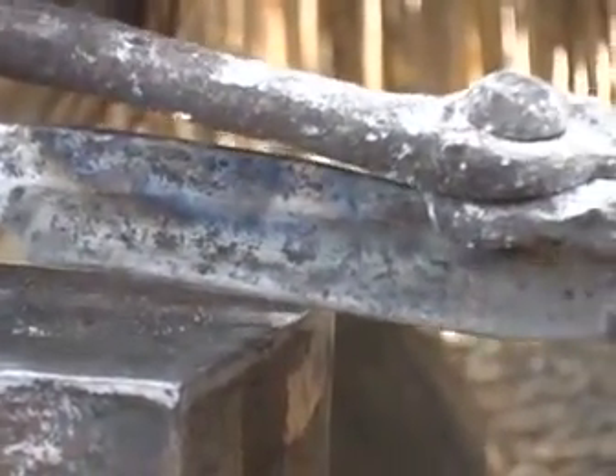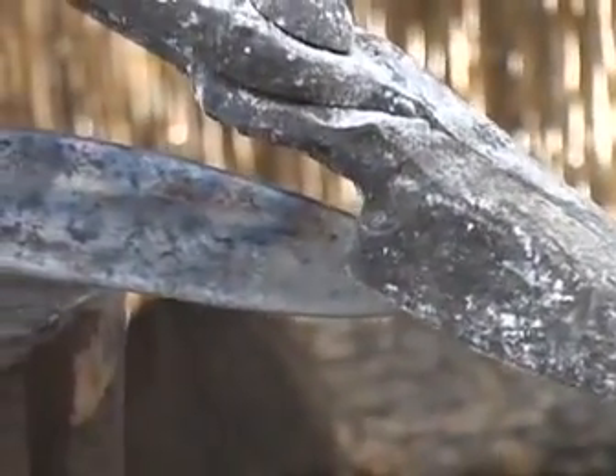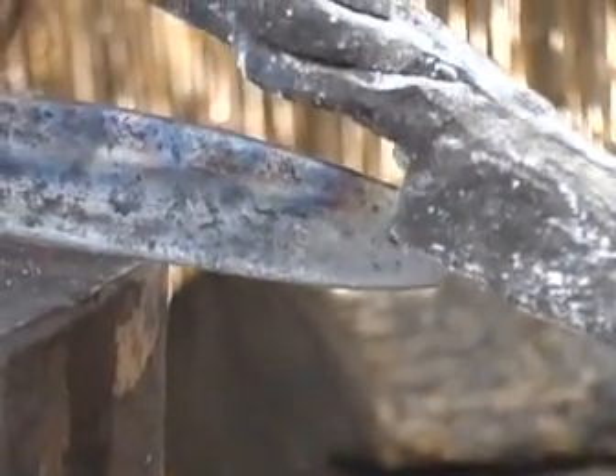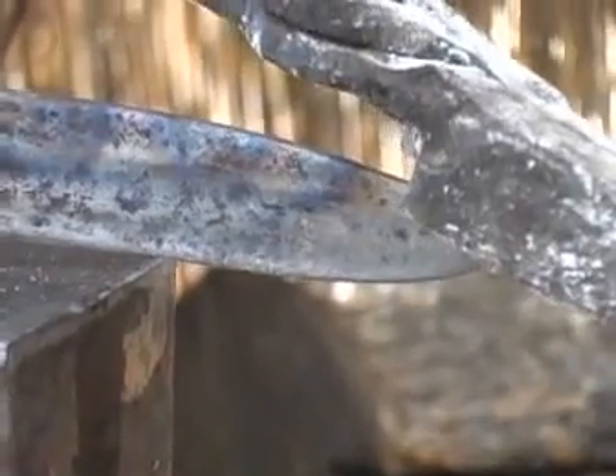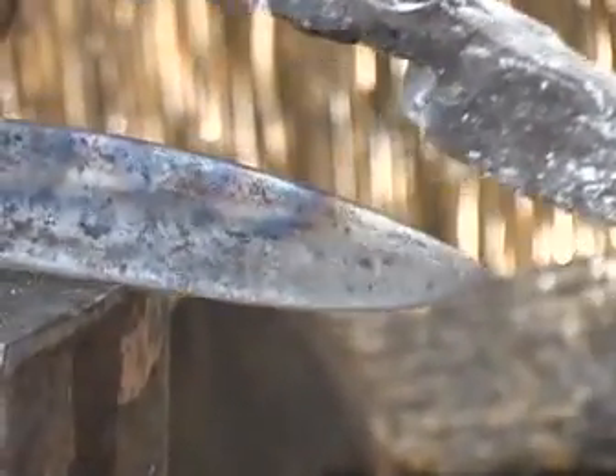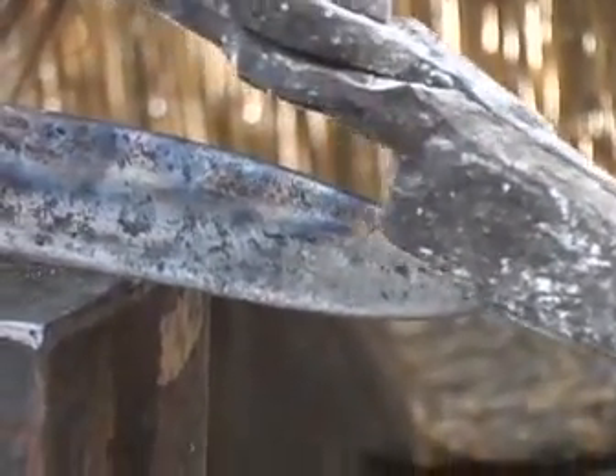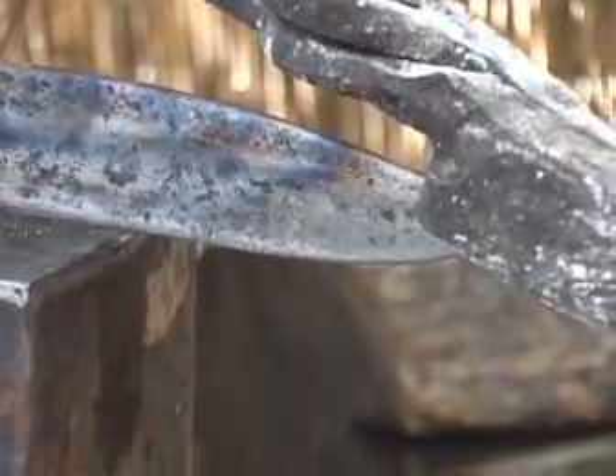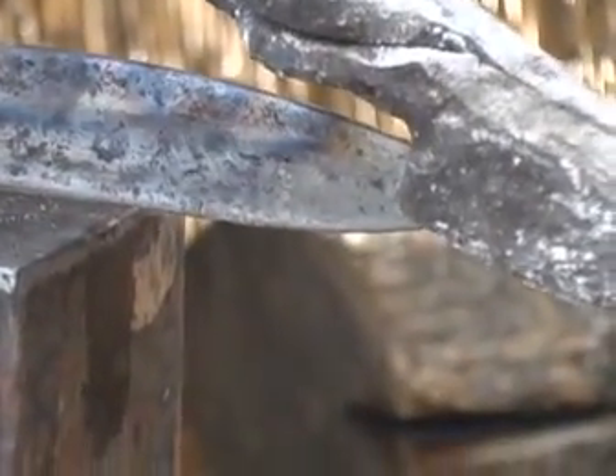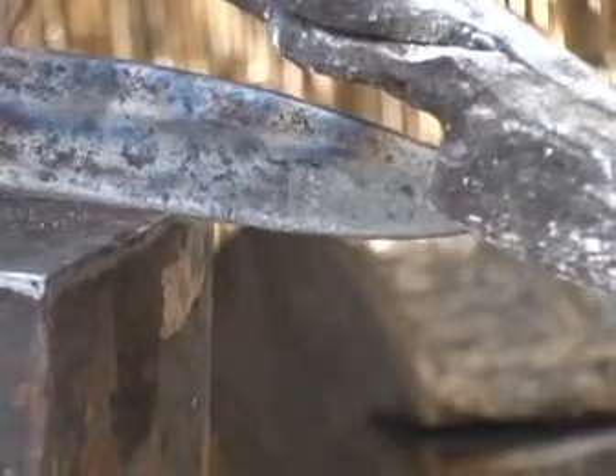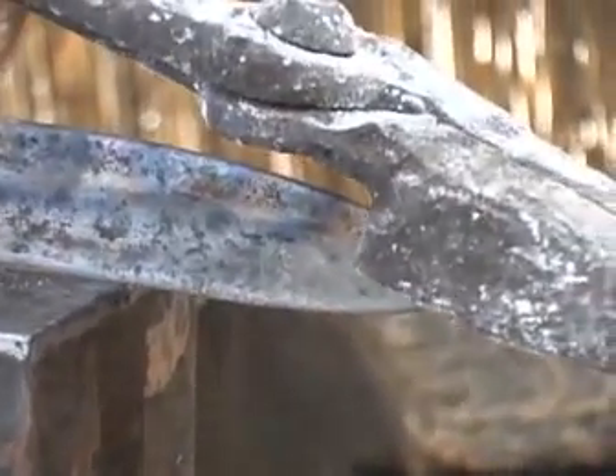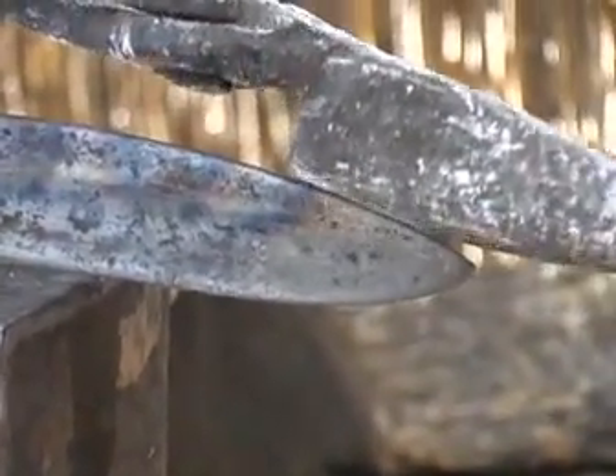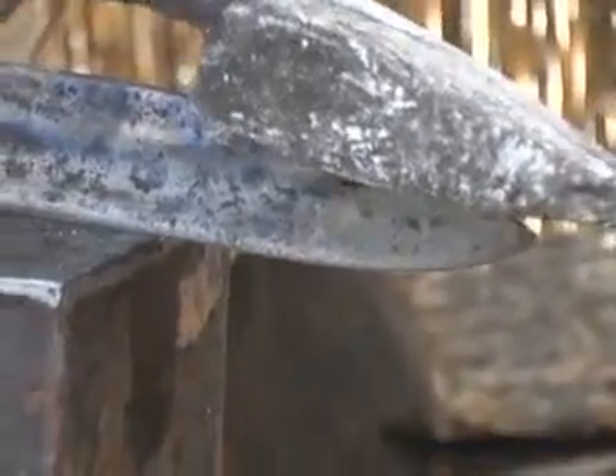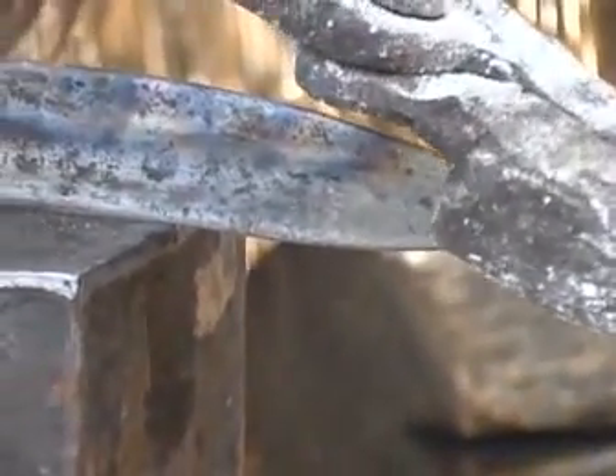I like to get the tip just a little bit softer because it's usually the weakest part of the blade. People don't realize how much pressure you can exert on just the very tip. So if you temper that a little softer, it'll hold up to abuse a lot better. You can do the same job with like a big chunk of steel or copper or whatever. All it is is just something really hot that you're touching the back with.